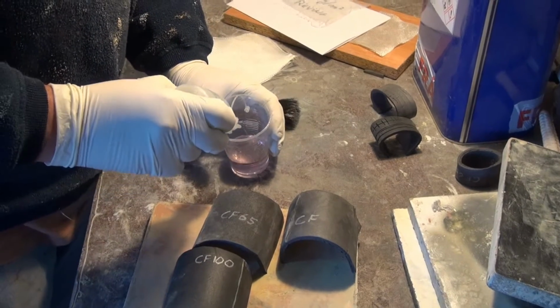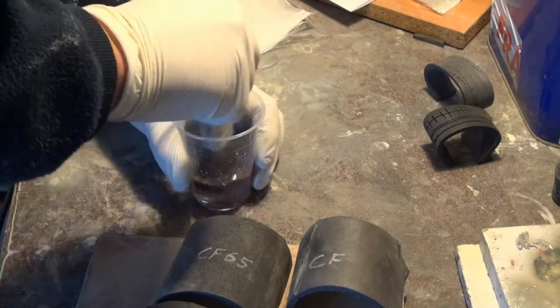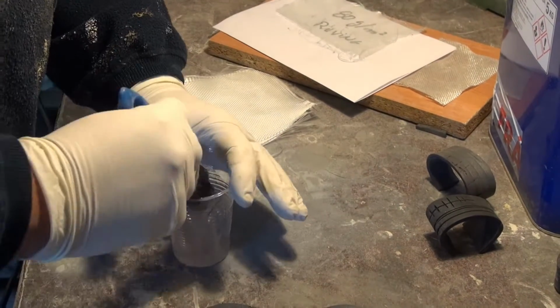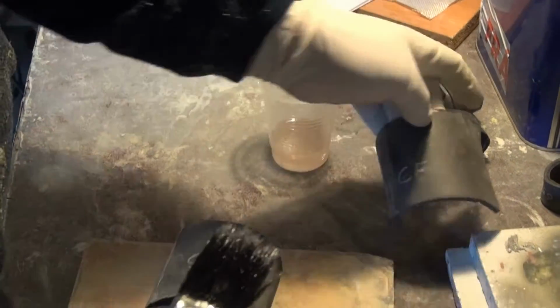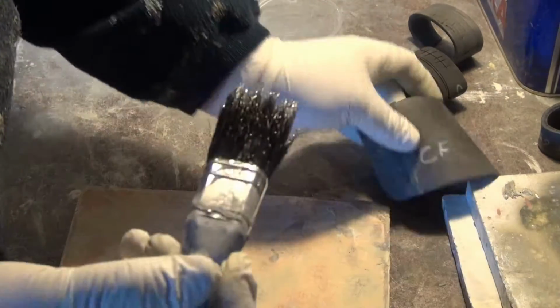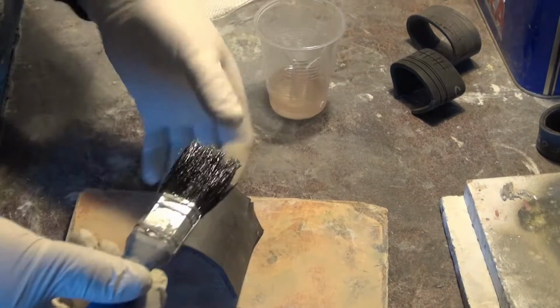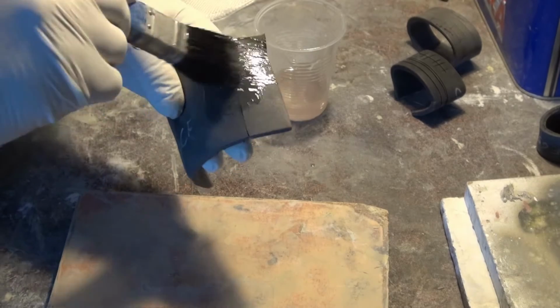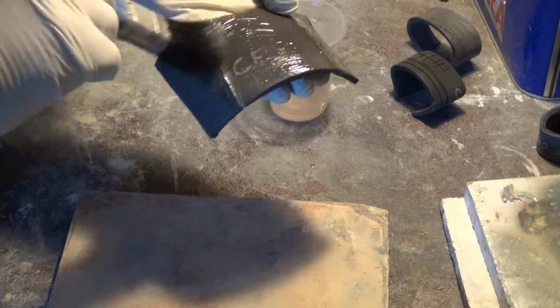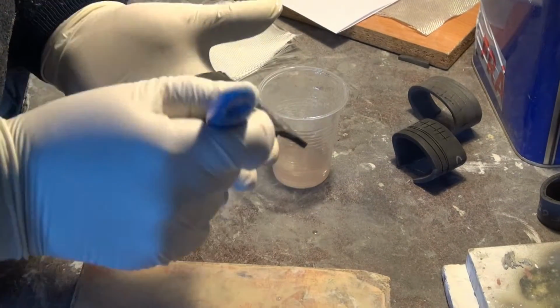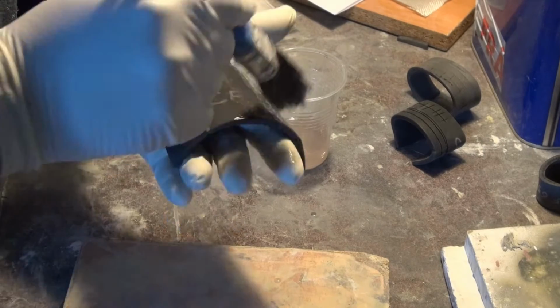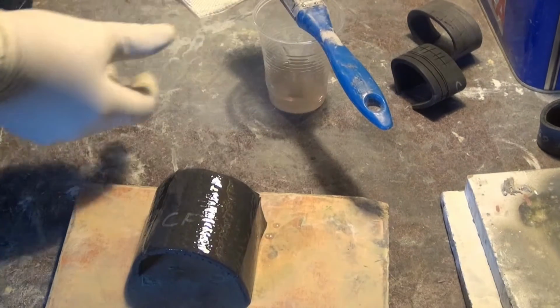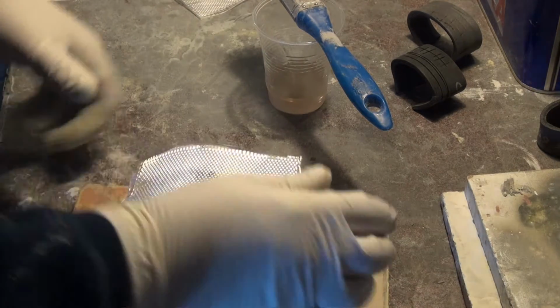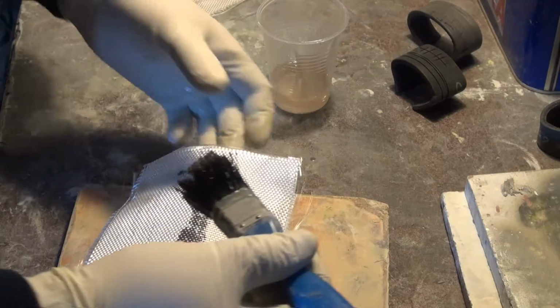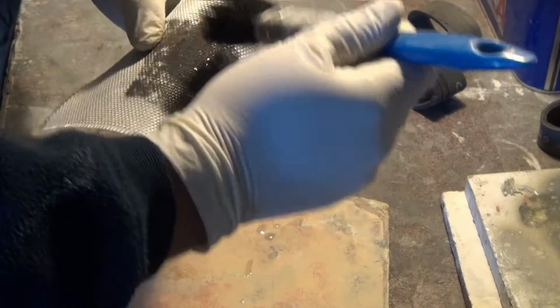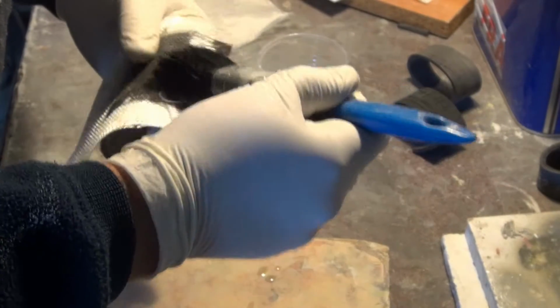We poured some resin into a disposable cup and added a catalyst according to the manufacturer's instructions. A thin layer of resin was applied to each of the pieces using a paintbrush. The fiberglass roving 165 grams per square meter was applied over the resin, paying attention for it to be fully stretched over the piece.